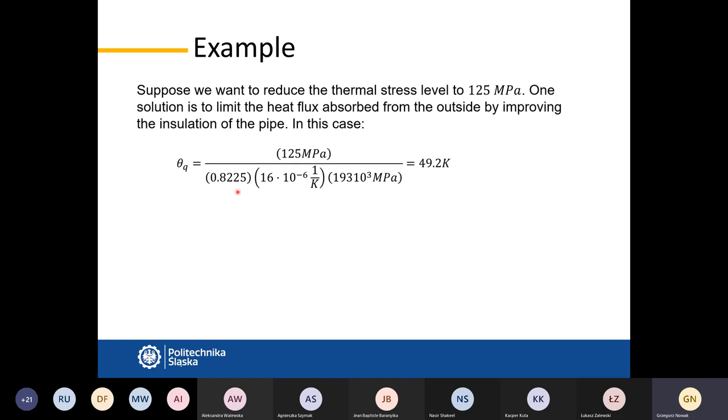For the same case, so 0.8225, lambda, and this is the, oh, there should be a dot, that's multiplied here. It's the Young's modulus, 193 gigapascals, so 193 times 10 to the third power megapascals. Here we have megapascals, here we have megapascals, so they will cancel out. So for such a case, this factor theta Q should be less than 50 K. We had previously 81. So it should be significantly reduced to have stresses not bigger than 125